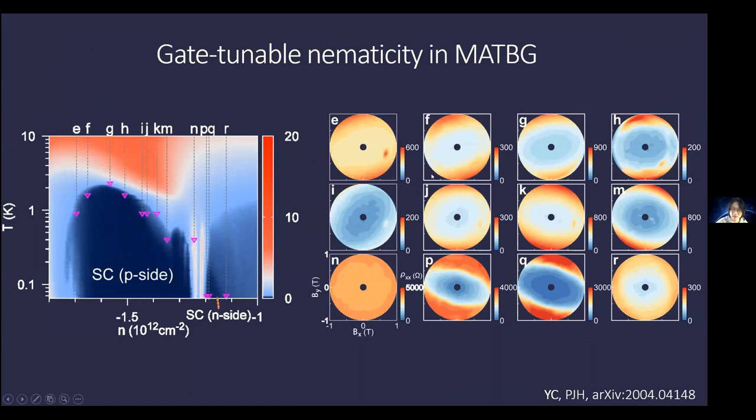But in general, you can see that, firstly, at all these points there is some degree of anisotropy, and the ratio is on the order of 1 to 2 or 1 to 3 along the minor and major axis of the nematicity. And also, what's important is that as a function of both doping and temperature, we see that this nematicity axis or director is indeed not locked to any particular direction, but shows some rotation as you change doping or temperature.